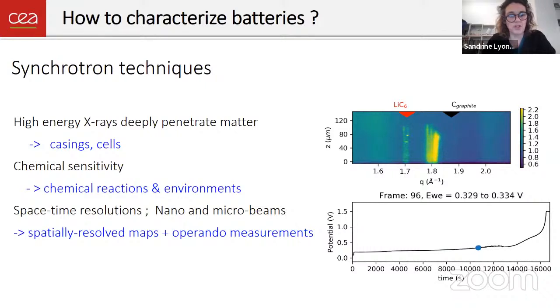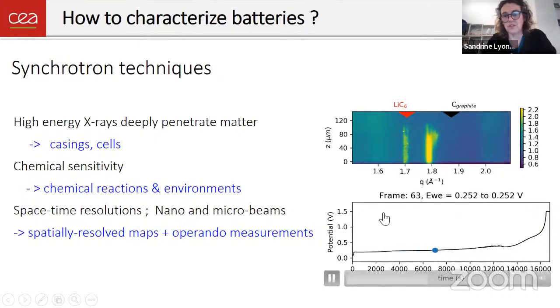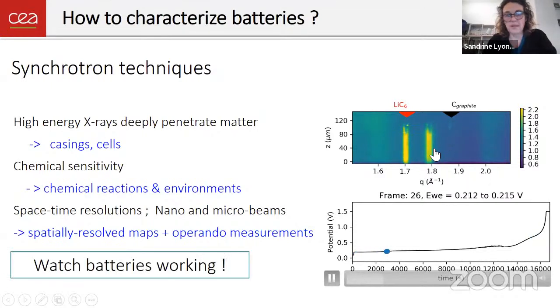And this is giving you the opportunity to perform some spatially resolved mappings of parameters of interest and what we call operando measurements, which is a measurement during the cycling of a battery. That's what you see on the screen. This is some kind of electrochemistry going on in a real cell. We are delithiating a material, and you see here a mapping across the depth of one electrode, in this particular case a graphite, and we are having Bragg peaks appearing, disappearing, corresponding to the removal of lithium from this highly lithiated phase to the fully delithiated phase. And this is real time during battery cycling. So basically what is really nice is that we can watch batteries working.